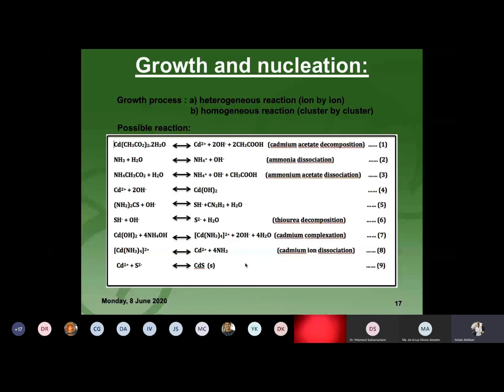In this mechanism, cadmium ion and sulfur ion first react in the solution forming the cadmium sulfide film, and then attach on the substrate. The possible reactions: here cadmium acetate and thiourea decompose into cadmium ions and sulfur ions.